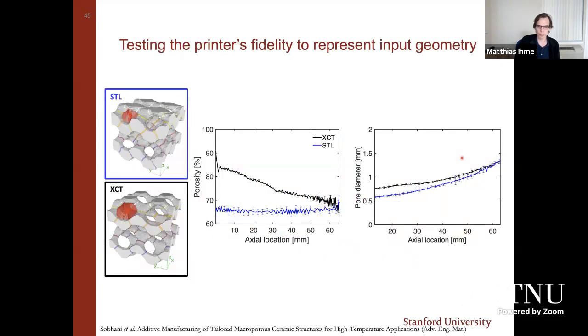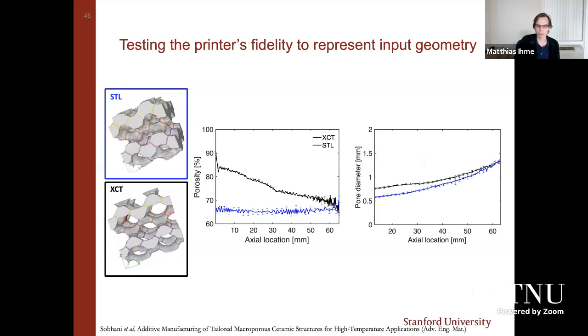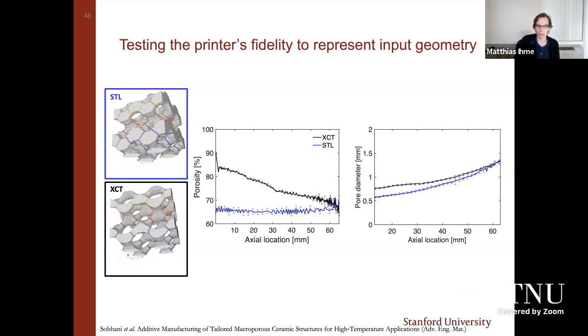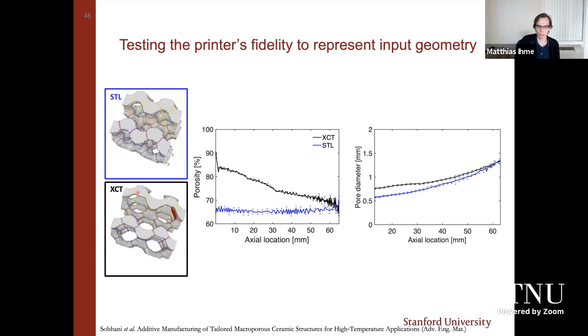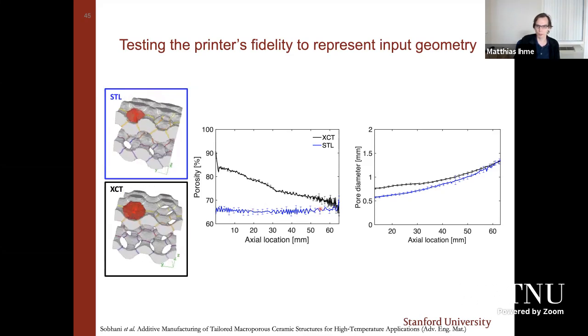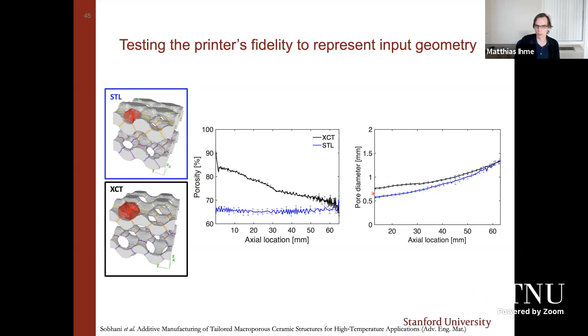The faithfulness of the process is illustrated here. What I'm showing you here is a CT reconstruction of the pore sizes, the STL geometry, and the XCT geometry. For the pore diameter, we're doing very reasonable. Black is the post-processed or the manufactured structure. The blue line is the geometry, the initial geometry.